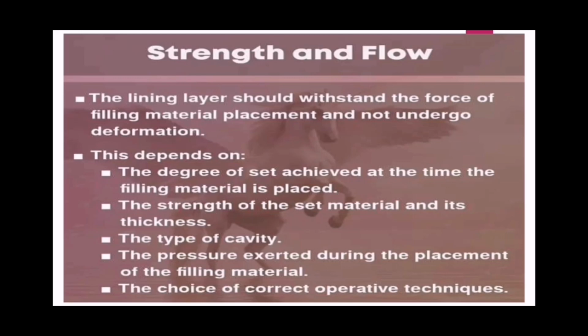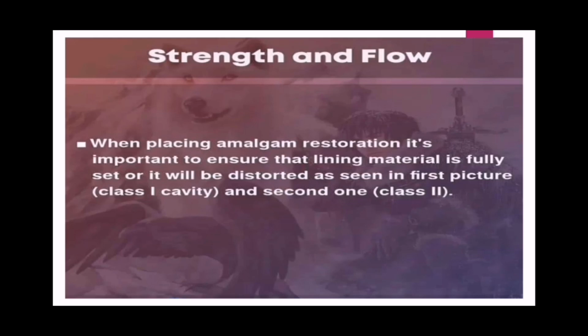Strength and flow. The lining layers should withstand the force of filling material placement and not undergo deformation. This depends on the degree of set achieved at the time the filling material is placed, the strength of the set material and its thickness, the type of cavity, the pressure exerted during the placement of the filling material, and the choice of the correct operative technique. When placing an amalgam restoration, it is important to ensure that the lining material is fully set or it will be distorted, as seen in the first picture.